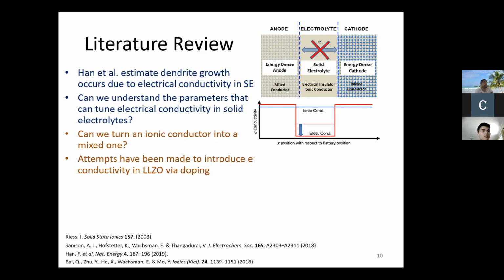Attempts have actually been made in some prominent solid electrolyte materials, in particular this lithium lanthanum zirconium oxide system. It's a garnet structure, and this was done experimentally, where they doped some of this material. The problem was, from the four different elements that they attempted to dope it with, it didn't do the job. They tried varying dopants, and some of them just didn't even form. They formed phase separations in the system. So one thing we hope is, can we find a computational design to explore the space better, rather than just brute force experiment?